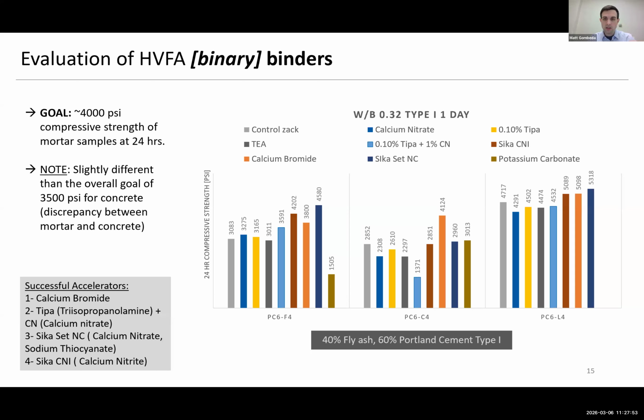And here's kind of how we narrowed down which ones we wanted to look at just from the mortar cubes at this point. Our goal was 4,000 PSI compressive strength at 24 hours of the mortar samples, knowing that if we scale it up to a concrete cylinder, we have a little discrepancy in strength there. So we wanted to be conservative when we started looking at these results. And there's, like I said, a lot of data here looking at different accelerator dosages and different types of fly ash. But the key takeaway is that we were able to exceed our goal of 4,000 for a lot of these different options that then helped inform what the concrete strength looked at.